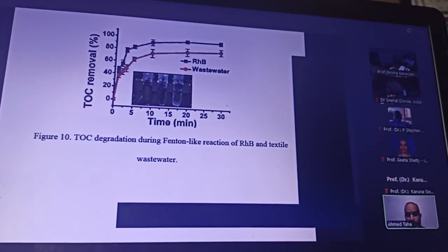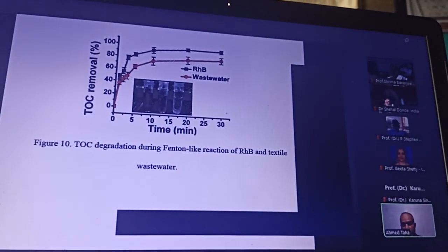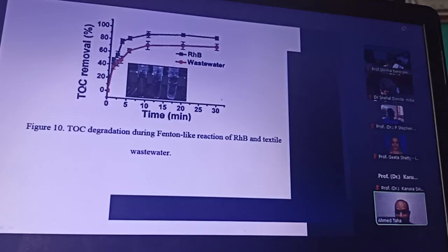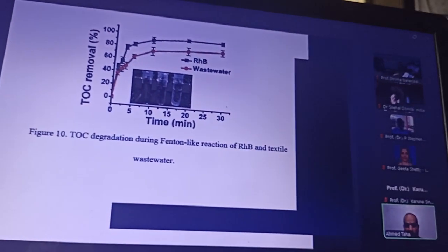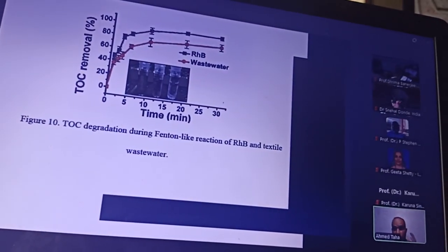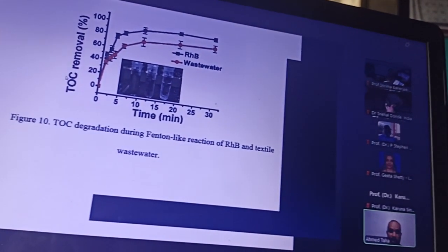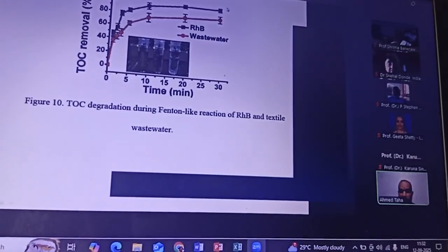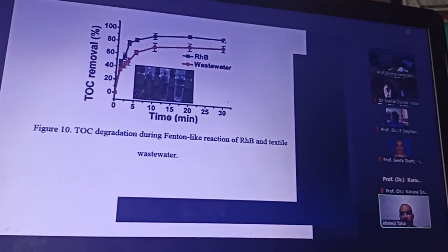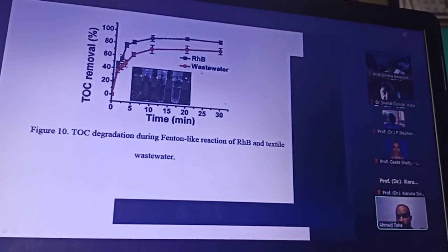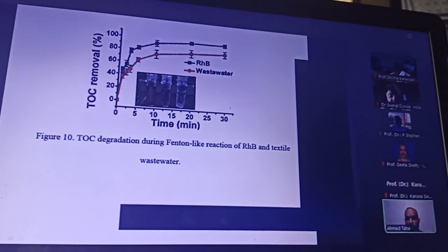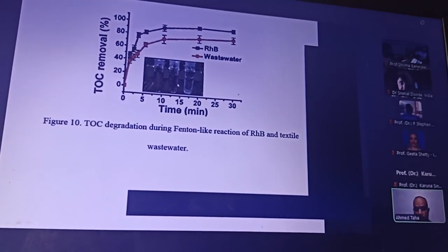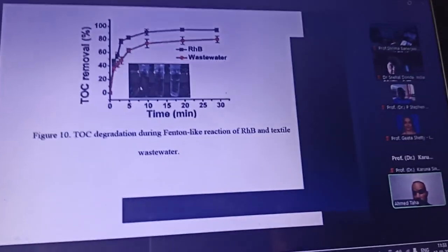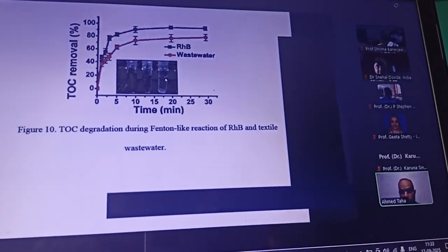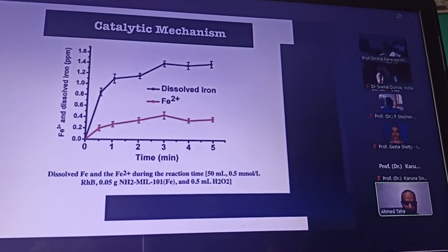And we applied the material, not only checking the color, but checking the total carbon. This gives us an accurate result about the real performance, not only because the dye may disappear while some organics are still there. So we studied the total organic carbon using the same dye, and we can say we get rid of more than 85%, about 90% of the dye. And for the real wastewater, you can see after 30 minutes we got about 80% removal of the total organic components in the wastewater. This was the textile wastewater, and this is the control, and this is after 30 minutes of running the reaction.